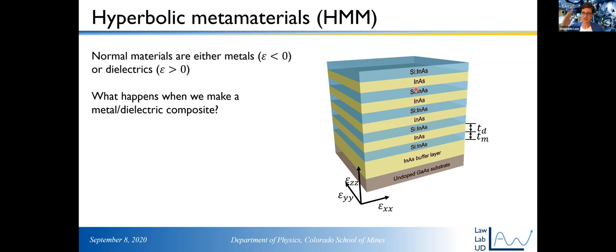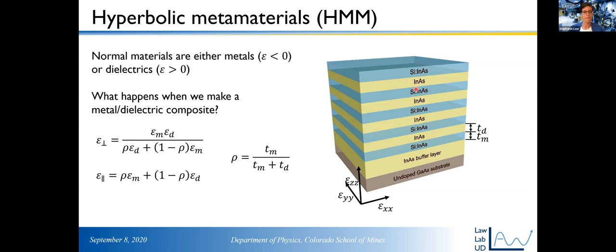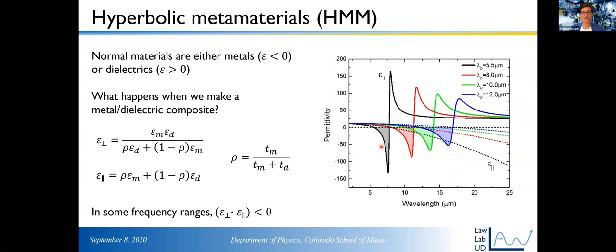Turns out, you can solve Maxwell's equations for this entire composite, and you get something called effective medium theory. And what you find out is that this composite material has one permittivity in the perpendicular direction, which is the z direction here, and a different permittivity in the parallel direction. It's anisotropic, right? It's different in this direction than it is in this direction. And in particular, in some frequency ranges, this composite acts like a metal in one direction and a dielectric in the other direction. It has a positive permittivity in one direction and a negative permittivity in the other direction. So if we just look at this black trace here, we can see that in this case, the perpendicular permittivity is negative in this shaded region and the parallel permittivity is positive. And then at longer wavelengths, the parallel permittivity becomes negative and the perpendicular becomes positive. Right, so this thing is acting like a metal in one direction and a dielectric in the other.